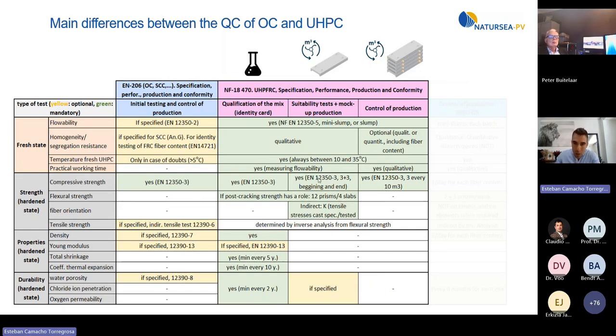In this part, we also need to do flexural strength tests on real elements, and this is where we obtain the very famous K, which means the ratio between the flexural strength in the real element and the flexural strength on the prisms of the previous stage. And finally, the control of production is the last column that you see, where it is mandatory to control the compressive strength. And curiously, in this part, it's not required to control flexural strength or even durability, because this is controlled in the previous stage.